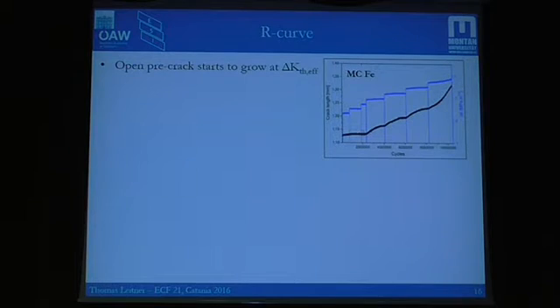Well, for the microcrystalline iron, due to our compression pre-cracking, we start with an open pre-crack because we have residual tensile stresses. So no crack closure mechanism should be active. When we reach the effective threshold, the pre-crack starts to grow. However, the crack can stop again when crack closure evolves, because the load at the crack tip gets reduced. So that's this classical behavior here.